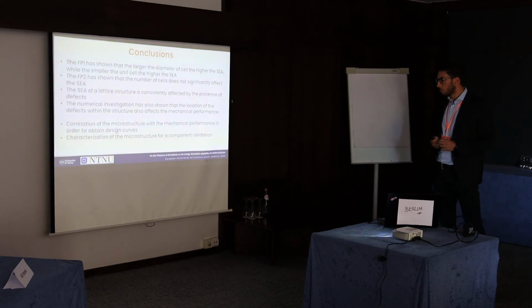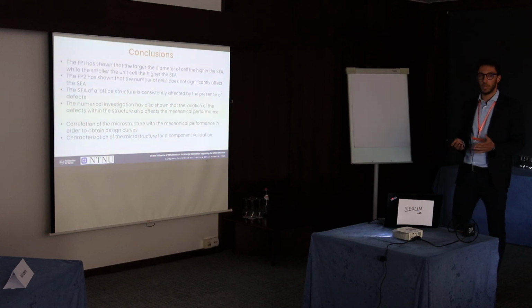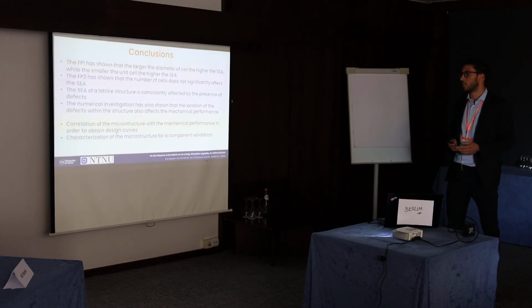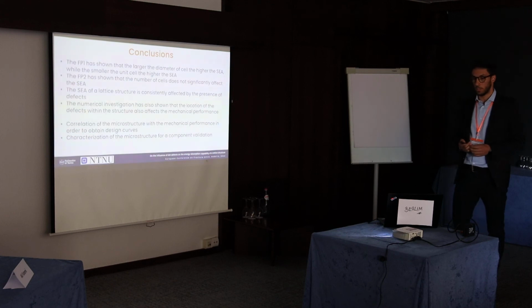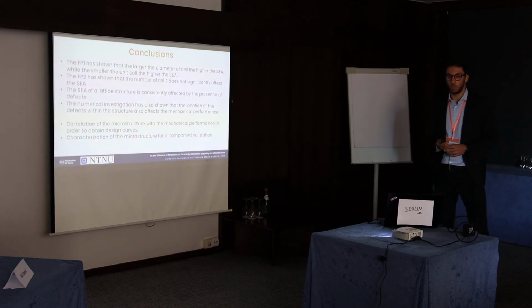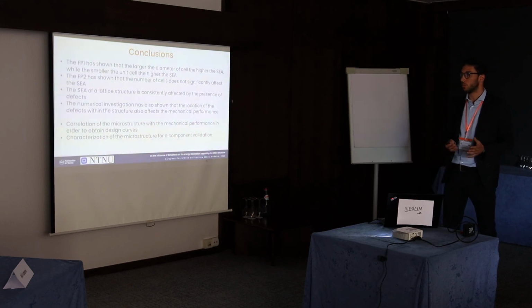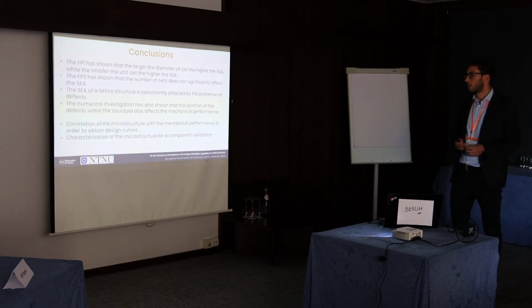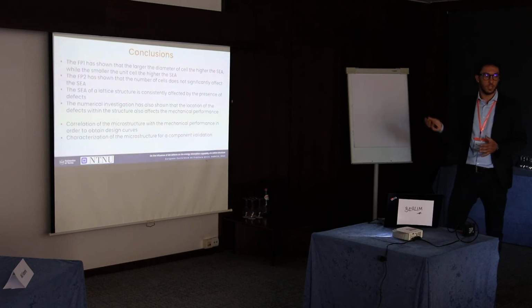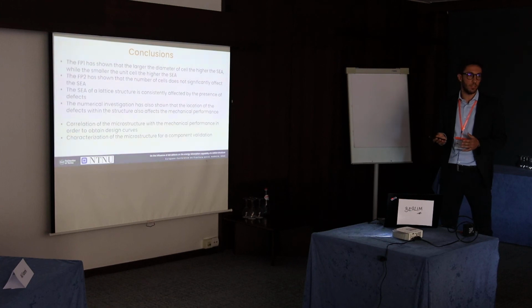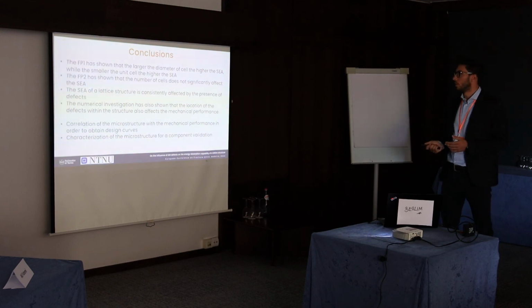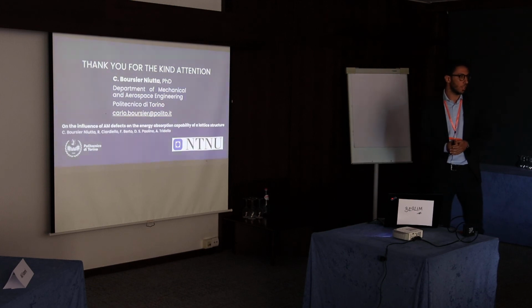And also, we have seen from the numerical analysis that the presence of defects consistently affects the specific energy absorption of the structure, and that the location is also another important parameter. So in the future, we intend to correlate the microstructure to the mechanical performance in order to obtain a sort of design curves, of the type that I've shown you before, so the specific energy absorption as a function of the defectivity. And also through these design curves, we can make a component validation once the microstructure has been characterized. So with this, I conclude my presentation, and I thank you for the attention.